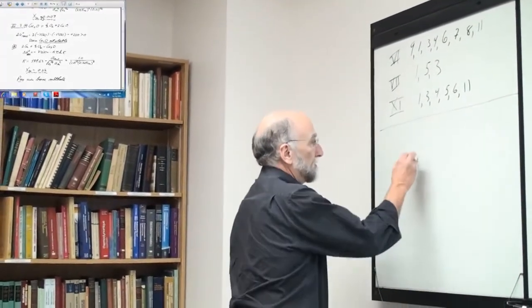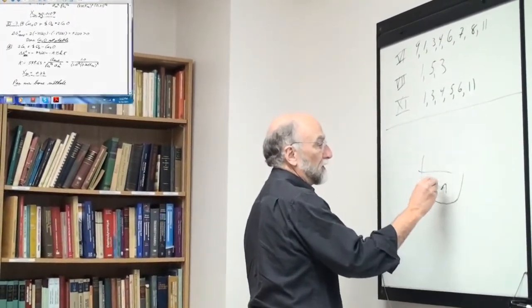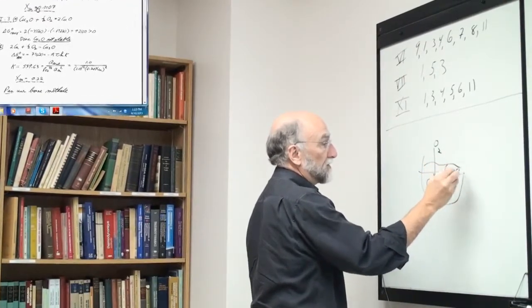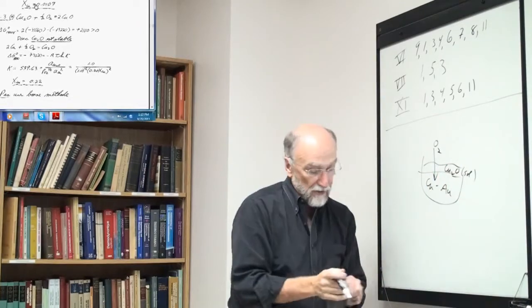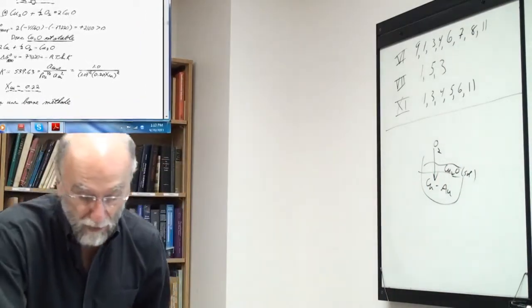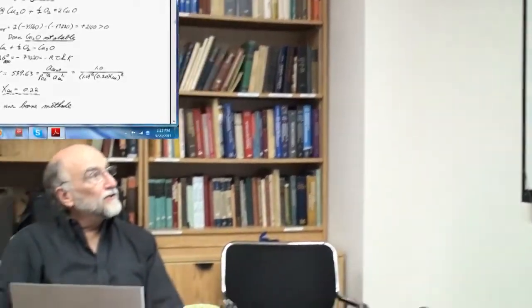Okay, so first of all, what you're going to do is bubble the oxygen. What we're assuming here is you take your liquid, this is your copper gold mixture, and you bubble your oxygen in here, and you're going to form copper oxide solid on the surface, and you're assuming that the gold doesn't oxidize, which it doesn't. So you only form copper oxide in that case.